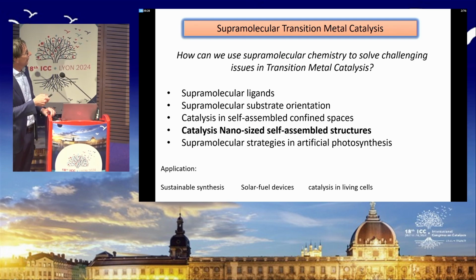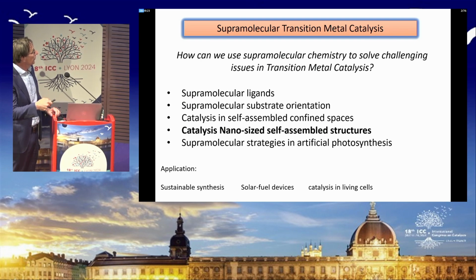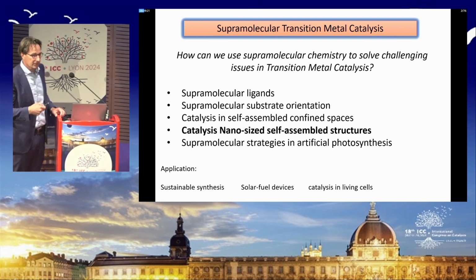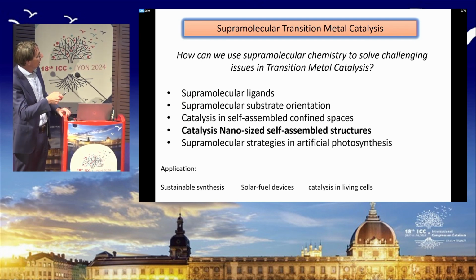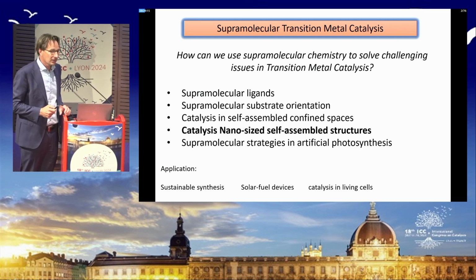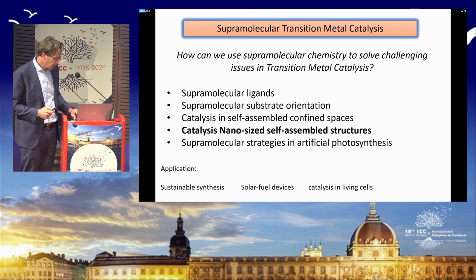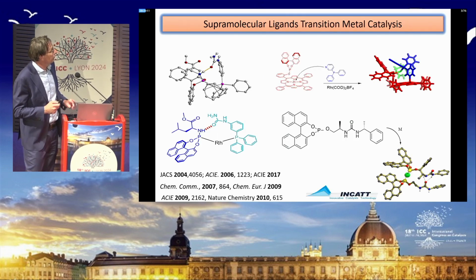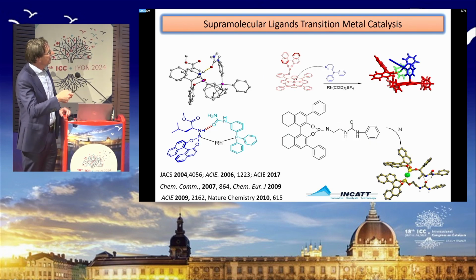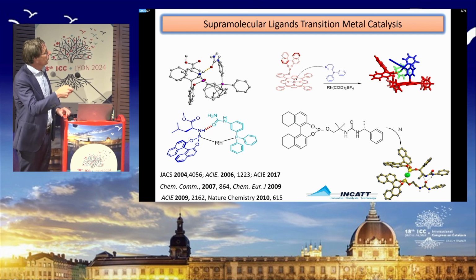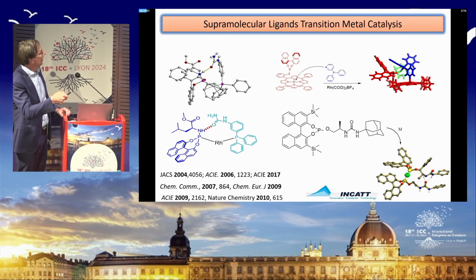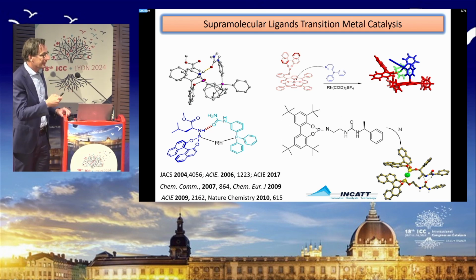using supramolecular chemistry. And over the years, we developed supramolecular ligands, supramolecular substrate orientation, catalysis in self-assembled confined spaces or larger nanostructures, and supramolecular strategies in artificial photosynthesis. To give you a bit of a flavor of that, so here you can see our first supramolecular bidentate ligand that forms by pyridine coordination, bringing together a phosphite and a phosphine. And here you see hydrogen-bonded analogues.